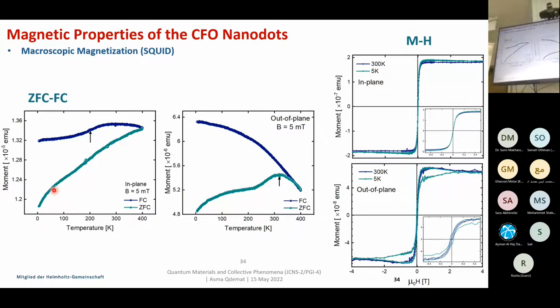In zero field cooling, we cool our sample from a higher temperature, 400 Kelvin, until 5 Kelvin in zero field. Then we apply a magnetic field, I applied 5 millitesla, and we heat it up from 5 to 400 while we're recording the magnetic moment. In field cooling, we cool it down from 400 to 5 Kelvin while the magnetic field is applied.